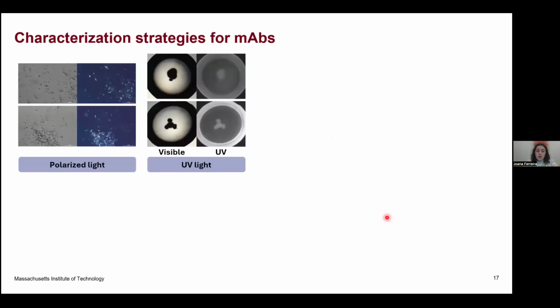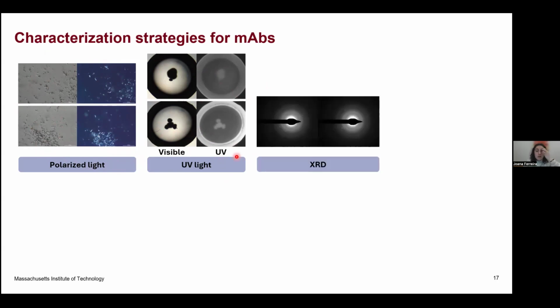So it's very nice that we observe some nice crystals, but we still need to ensure that those are in fact protein crystals. So most of the labs can use polarized light. However, with polarized light, the crystals might still be shiny, but they might be salt crystals. So the second step is to use UV light. This gives us direct information if we have or not a protein crystal. We also have tried XRD. However, with the in-house source that we have access to here at MIT, we could only see that we don't have salt crystals, but it was not possible to obtain a diffraction pattern.